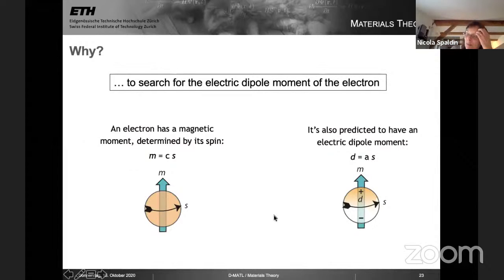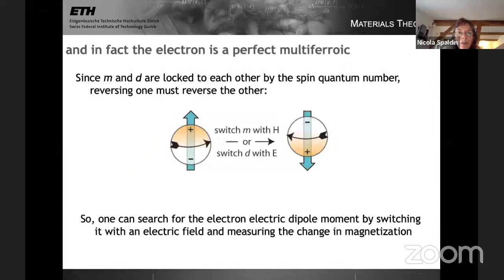So this, of course, is very exciting because exactly what we couldn't do so easily in bismuth ferrite. In bismuth ferrite, we couldn't switch by 180 degrees the electric polarization and get the magnetism to switch. We had to use this trickery of it going around the different axes. In an electron, because the magnetic dipole and the electric dipole are locked to each other by the spin quantum number, if I switch the magnetic dipole with a magnetic field, the electric dipole has to switch. Or if I switch the electric dipole with an electric field, then the magnetic dipole has to switch. So the electron, in fact, is our perfect multiferroic. We didn't have to look as far as we thought we did. We have a multiferroic in the electron.